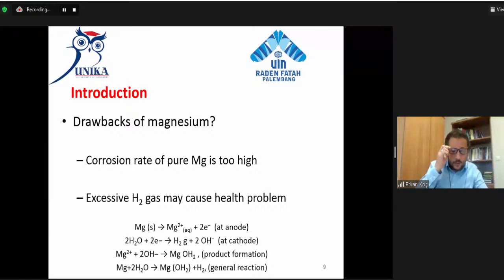Also, magnesium is known to corrode in an electrochemical reaction, which produces magnesium hydroxide and hydrogen. Within the human body, magnesium degrades according to the cathodic reaction, leaving hydrogen gas bubbles and magnesium hydroxide. These hydrogen bubbles may cause physical problems such as blocking your bloodstream. If the hydrogen bubbles are formed slowly enough, they will have time to diffuse into the tissue. So you cannot use pure magnesium.